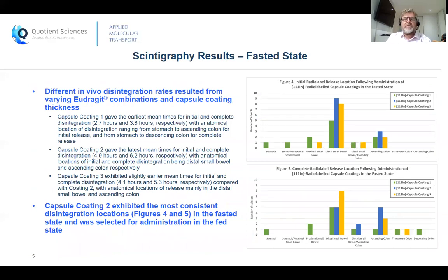The fasted scintigraphy results for all 3 coated capsules are shown here in the slide. The bar charts on the right have GI locations of release on the horizontal axis and the number of subjects on the vertical axis. Figure 4 shows the gamma scintigraphy derived locations for initial release, whilst Figure 5 shows complete radiolabeled release, where there's no longer a core of radiation visible in the gamma camera images. Some GI locations are joint, where the radiation is observed across both locations in that specific image.